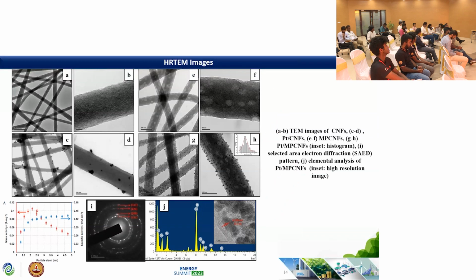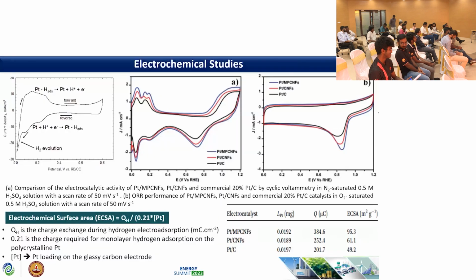So this itself will indicate that the performance will be better than the commercial electrocatalyst. For that, we also tried to do all the material characterization, and then further we have to prove that it is electrochemically active. So for that, we performed electrochemical analysis like cyclic voltammetry. Initially we tried to evaluate the electrochemical surface area. For this, we used CV in nitrogen saturated sulfuric acid solution.